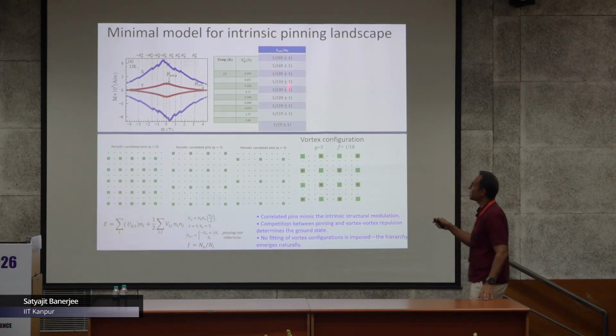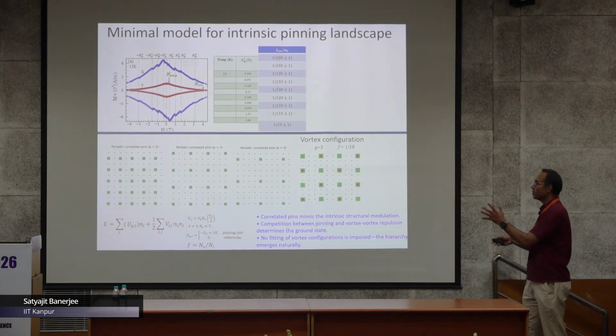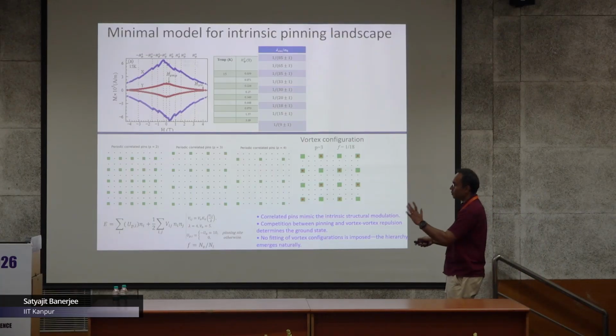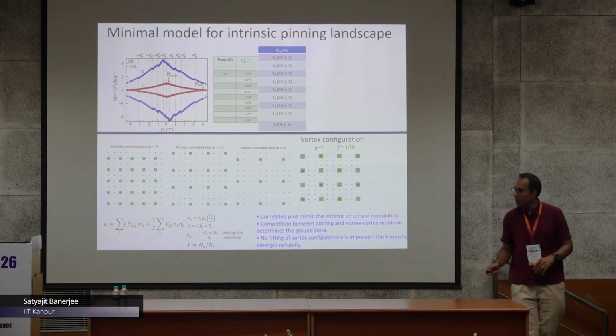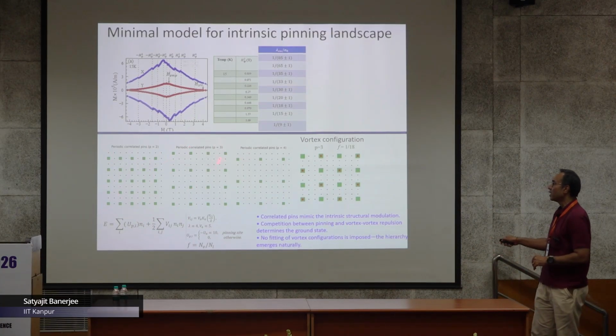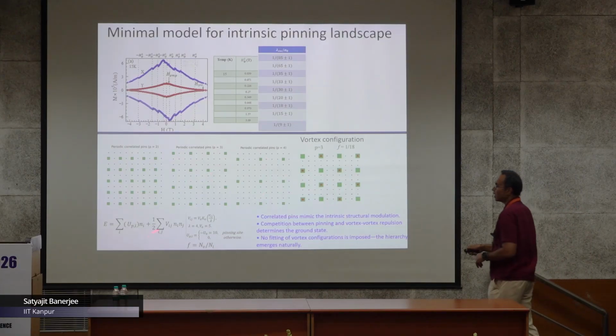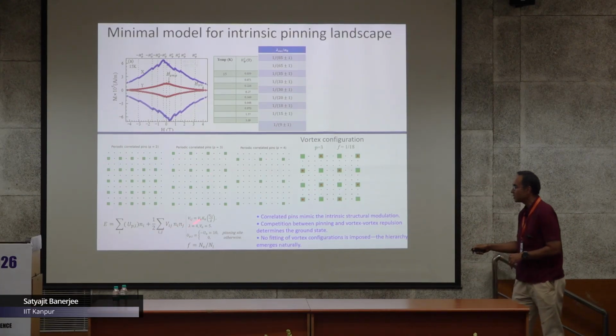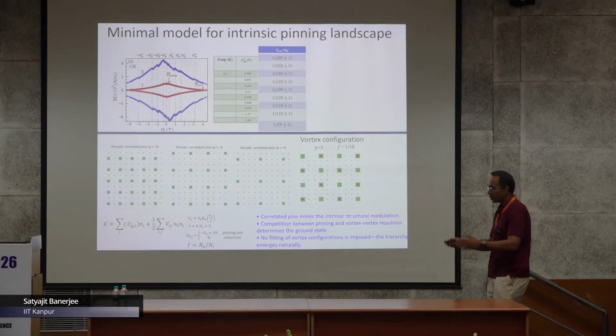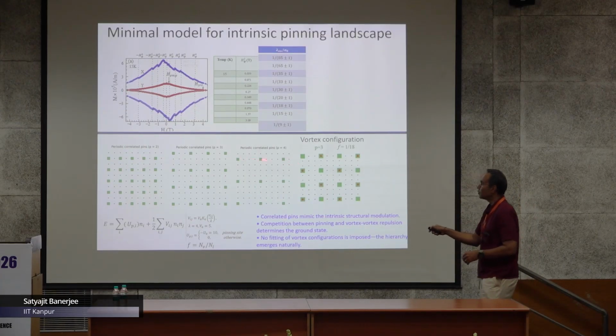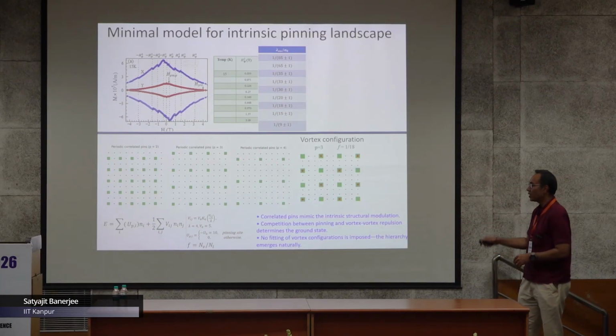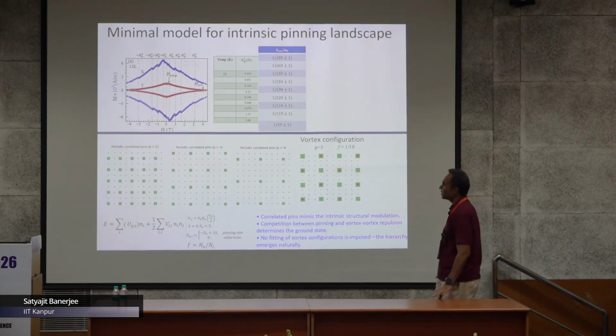We have a simplistic Monte Carlo type of model where you have periodic pinning inside the crystal, and then we put vortices inside the system. These vortices are thrown in, and you can vary the periodicity of the periodic pins generated inside the system.